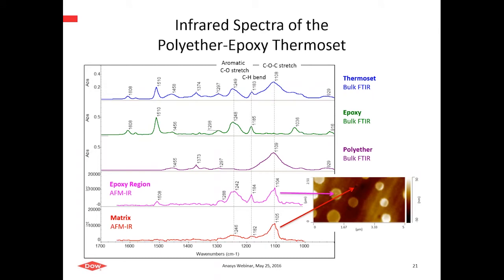So if we look at the IR spectra now of this morphology, here we have essentially the bulk IR shown at the top. We see components that we know come from, in the bulk, both of the separate components shown in green and purple below. So the epoxy, for instance, shows strong absorbances due to carbon-oxygen stretch and CH bending modes. The polyether shows strong carbon-oxygen-carbon stretching that's absent in the epoxy itself, but of course when they're blended we see all 3 of these features. So this helps us understand ahead of time what frequencies we want to go after in mapping and studying this morphology. We can get spectra, of course, in each of the parts of the morphology.